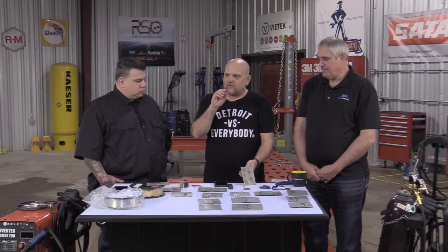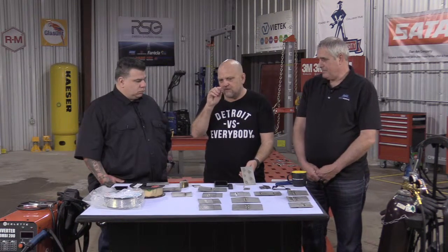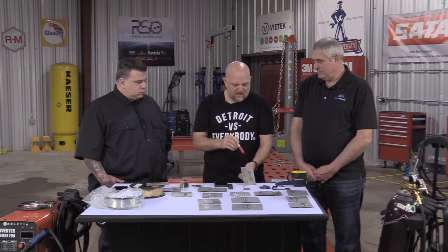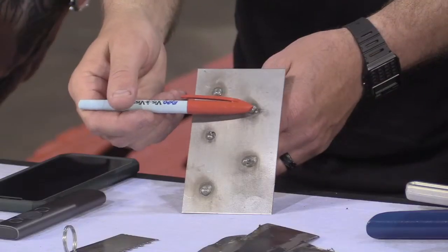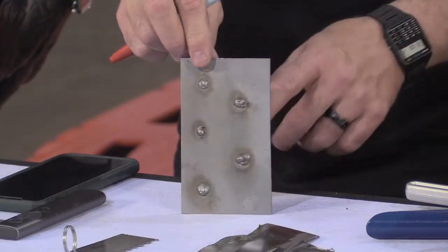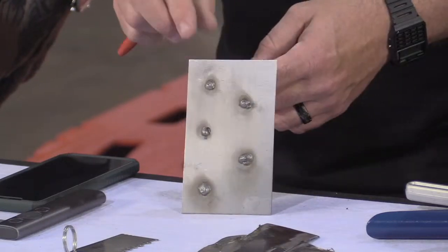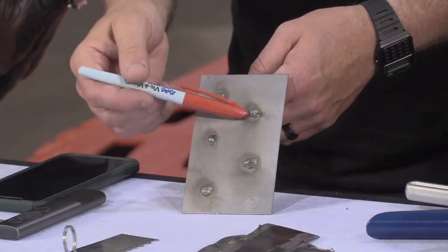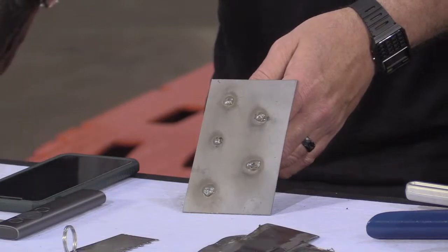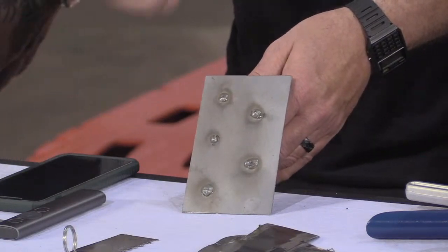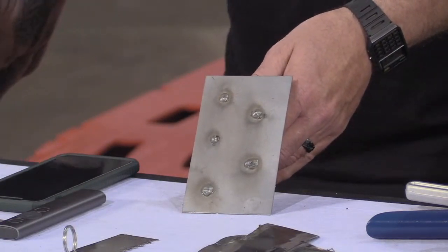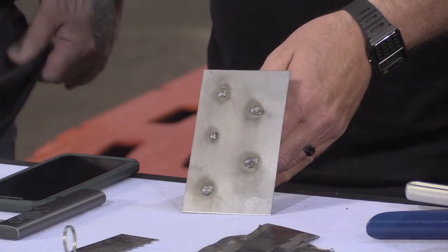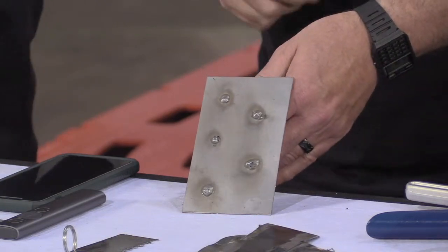Bigger ones, fine. But on a smaller one, when I'm going around that hole, if the material starts to flow over that edge before I get to the center, I could have a high weld with no penetration. Now this one's got a little bit of penetration. I wouldn't be super happy with it, but that's one thing that can happen if I start on the outside of a 6mm. So my preferred style, personally, again, this is my technique, is right in the middle, zzz, and then a real quick circle around. That way you're going to get penetration.